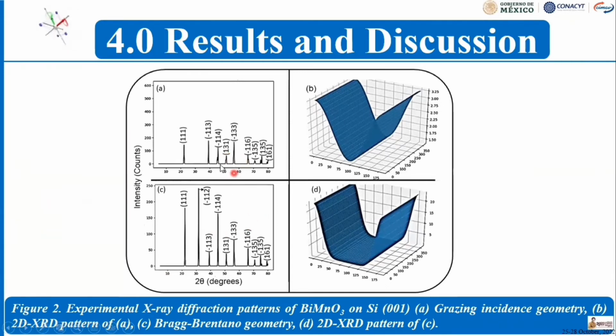Results and discussion. Here we have the different geometries of our experimental results. A is the grazing incidence, denoted here with the 2D XRD pattern, and C here is the Bragg-Brentano, also represented with its corresponding XRD pattern. The intensities here are not as intense as the Bragg-Brentano results, and we can see that the peak that is more intense in the Bragg-Brentano is practically invisible here.